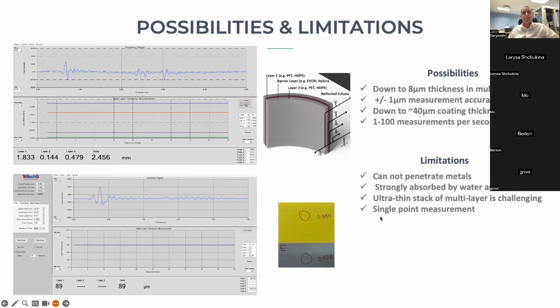So let's look at what are the possibilities and the limitations for any technique. Each gives you some possibilities as well as some limitations, right? So in terms of the possibilities, it is a useful technique for multi-layer structures, as long as each one of those layers is separated in a way that the echoes coming back from them are relatively easily distinguishable in the system. Then we have demonstrated that a layer down to 8 micron, and we have even seen 5 micron thickness, can be resolved with this technique with a ±1 micron measurement accuracy.